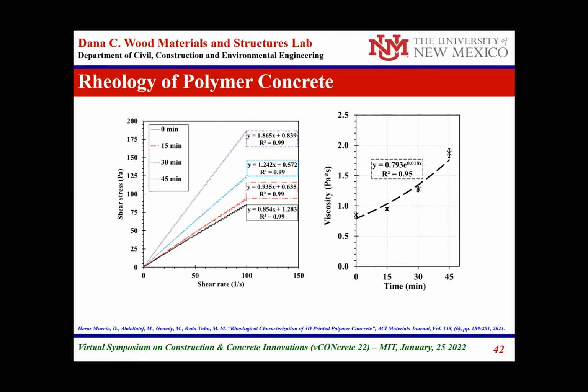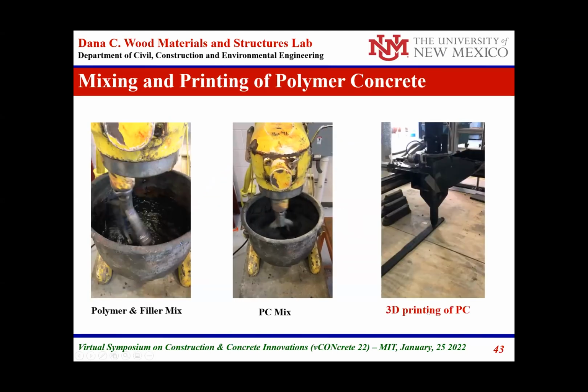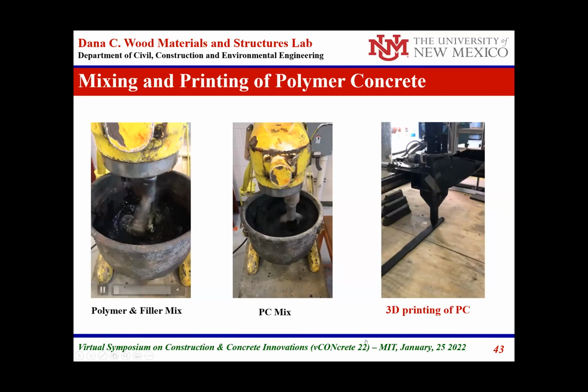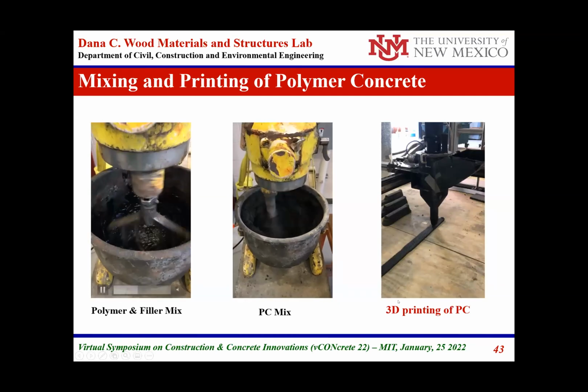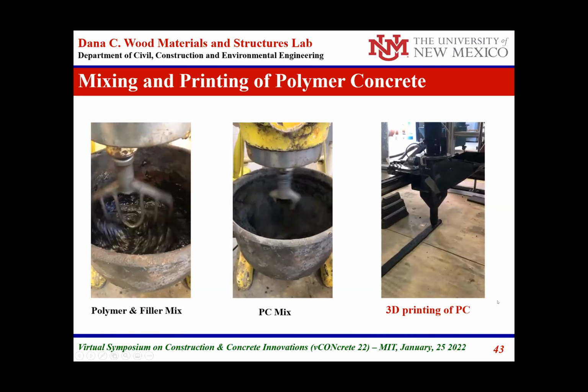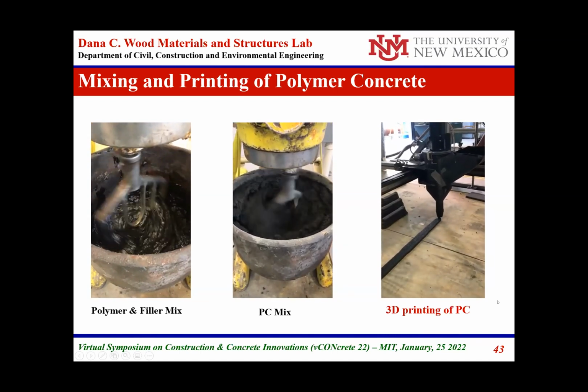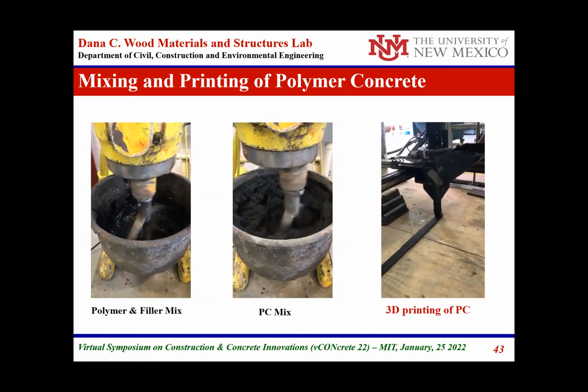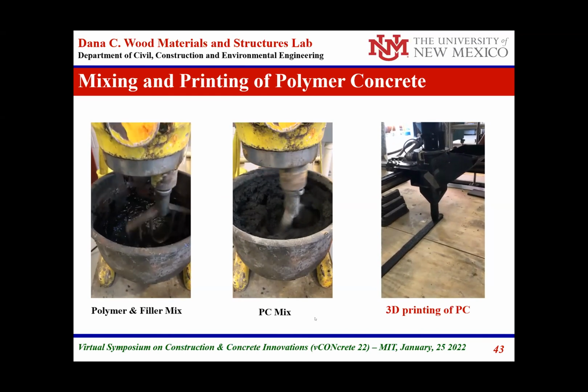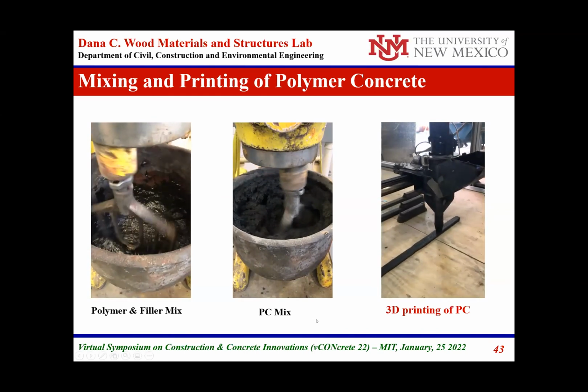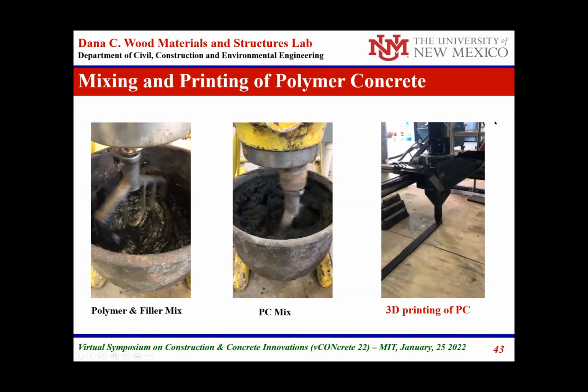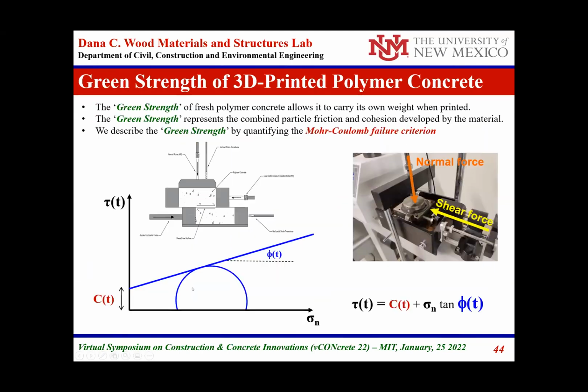This is the polymer matrix before we actually add the concrete aggregate to it. These videos show the mixing of the polymer and the filler, then adding the aggregate, and then the 3D printing of the polymer concrete layers. This is the 3D printed polymer concrete mix using Novolac epoxy for polymer concrete 3D printing.